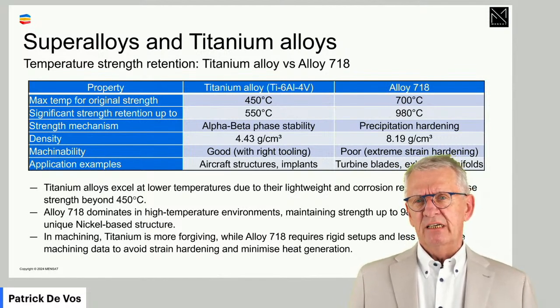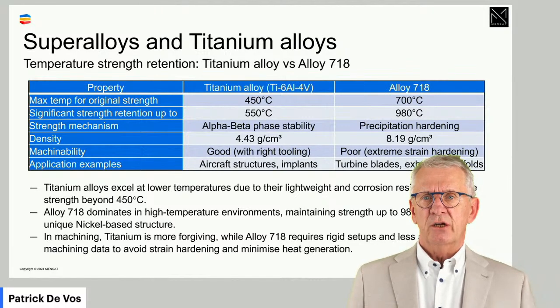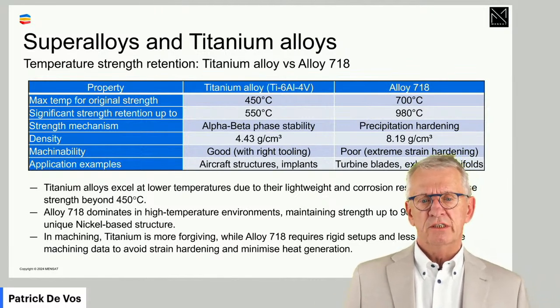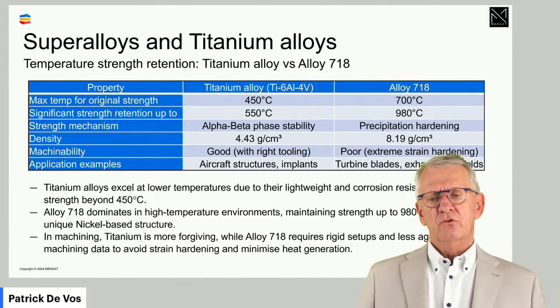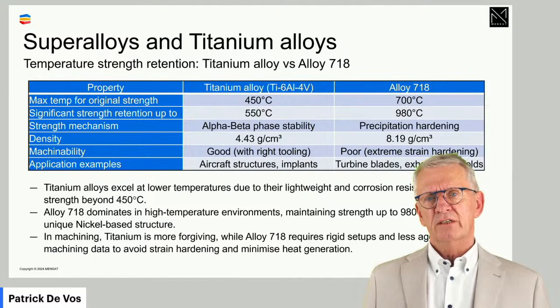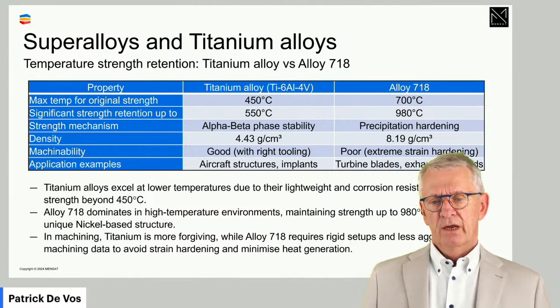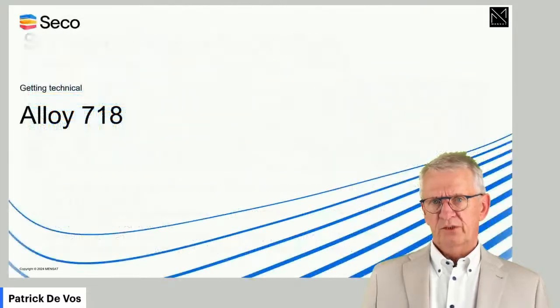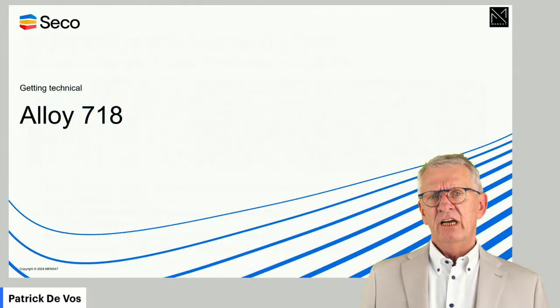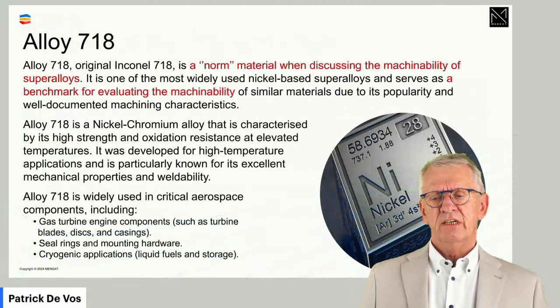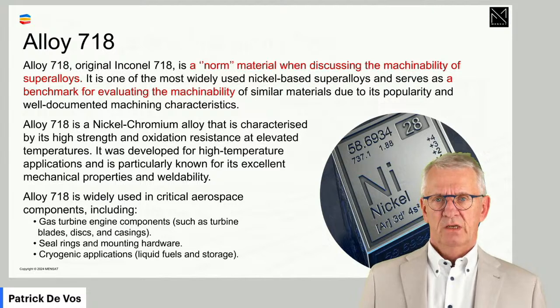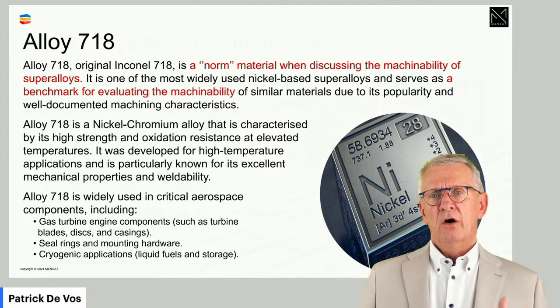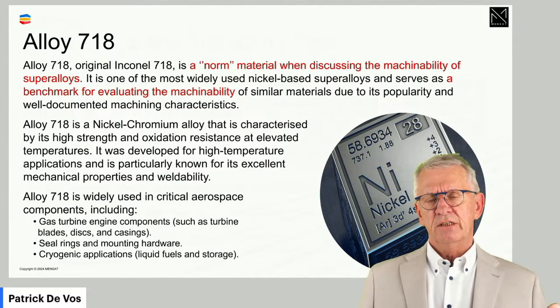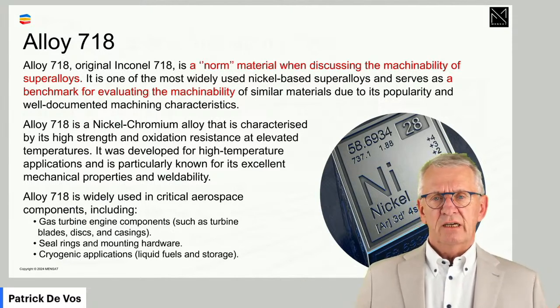The machinability, I mention already here as a general picture, but later on, of course, we go much more in detail. I would say if you compare the two, machinability of a superalloy is lower than the machinability of titanium. But I specify that more in detail later on. Now, alloy 718, I already used the word a couple of times. One of the original superalloys, and still today quite a lot used, is that so-called Inconel 718. Inconel 718 is a commercial name of a material which basically contains around 53% nickel, with a lot of properties